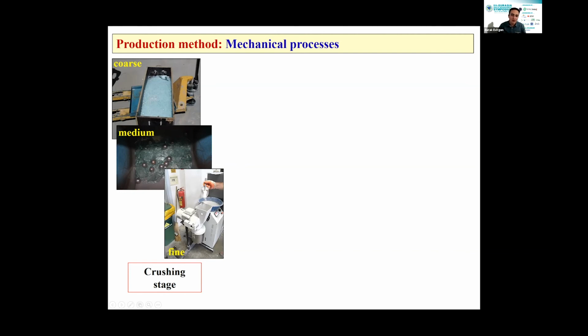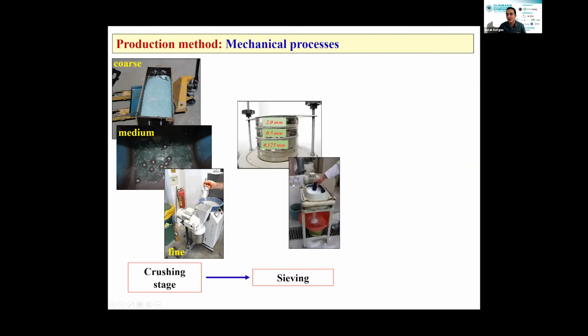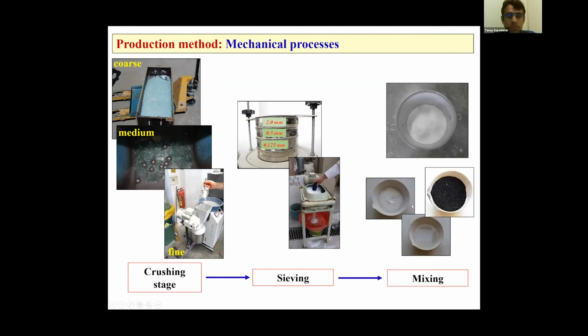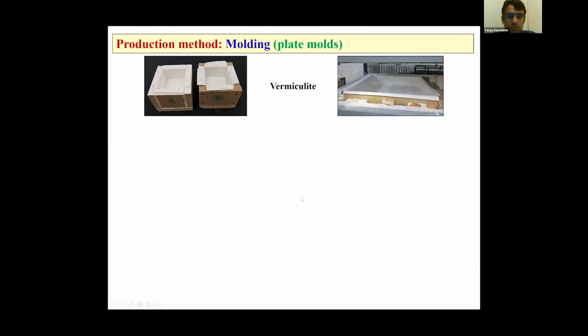And then the final stage requires the grinding process also. After these processes, we pass to the sieving stage, and it is raw material, only waste glass powder, and we sieve it up to the 100 micron level, and then the mixing process comes. Raw material and the forming agents were mixed together. The molding stage, I think, is the most important stage of the production method.